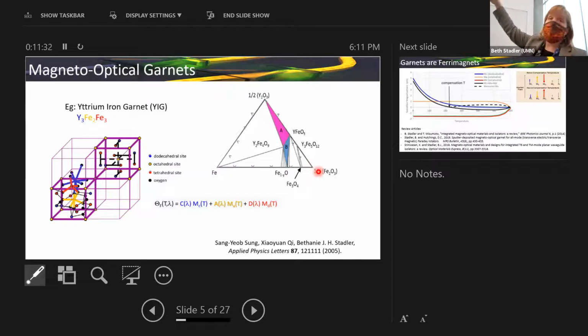If I could look at the edge of that triangle, what I would see is that if I have all yttrium and oxygen, I'd get this Bixbyite structure. If I have half and half yttrium to iron, but still 1 to 1 to 3 oxygen, I'm going to end up with this perovskite-like structure. And then there's garnet if I get 3 to 5 to 12. And finally, if I'm fully at iron and just oxygen, I'll get this hematite phase.